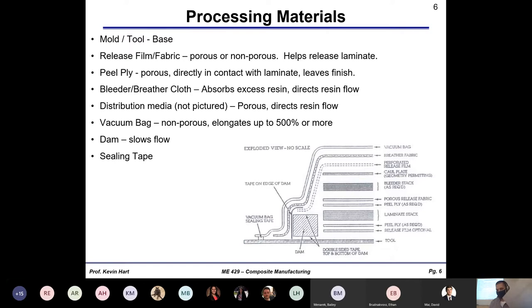All right. So here's an aluminum plate, and I laid this down on top of that aluminum plate. Now, one thing I talked about last time is that in order to be able to remove this particular piece off of the aluminum plate after the manufacture, you have to have what's called the release film. All right. It's a non-porous film. And that's what's actually on this side here. So we can probably see this on the camera. It's a very thin nylon film, basically. It's not nylon. It's actually ETFE is the actual polymer here. These blue pieces here are tape that's meant to hold the film down.